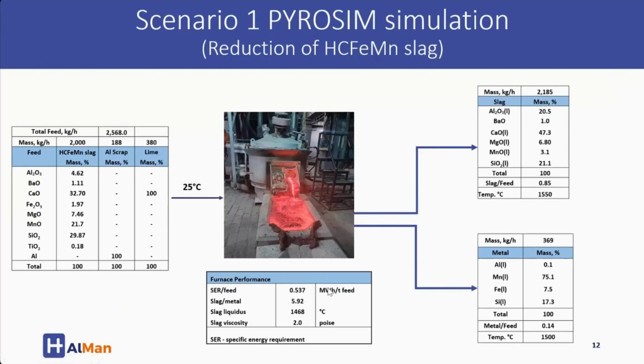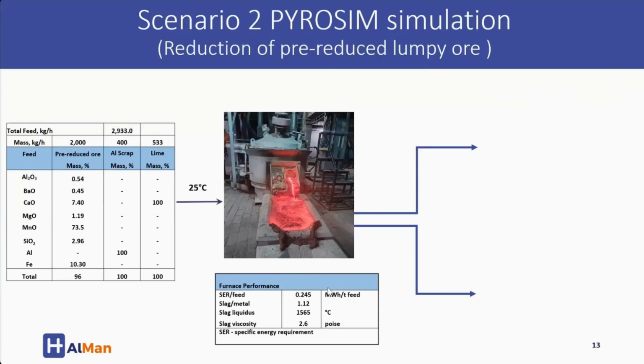Scenario 2, we looked at smelting of pre-reduced lumpy ore. In this case, for MINTEK we only generated 300 kgs, and the pre-reduction didn't progress far enough. So for this work, we actually used pre-reduced lumpy ore that was smelted at Sintef by Caspar, as he explained. They managed to ship it to us, and the composition shown here is from the work Caspar did at Sintef.